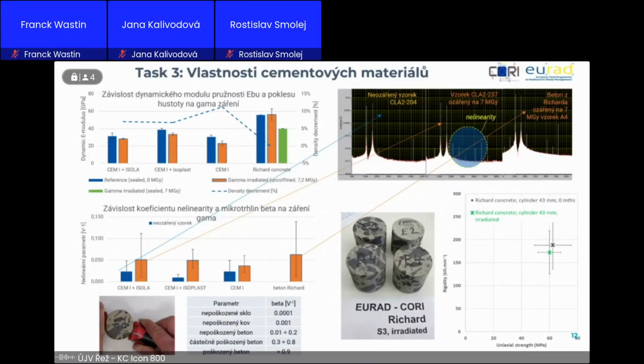So let's go to the left-hand side picture. When I was testing a sample with plastificator Isola, before irradiation is the blue one, after irradiation is the orange one, and it's increasing. There are more cracks. The same with the plastificator isoplast. The higher the irradiation, the more microcracks. When there is no plastificator, suddenly there are not so many cracks.